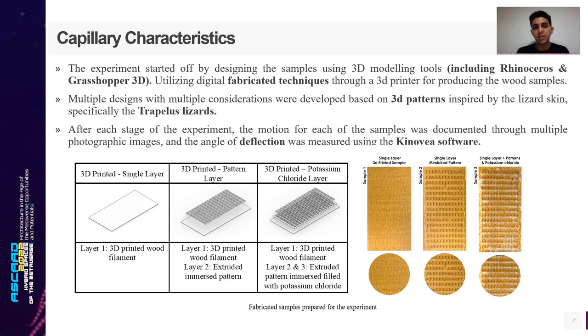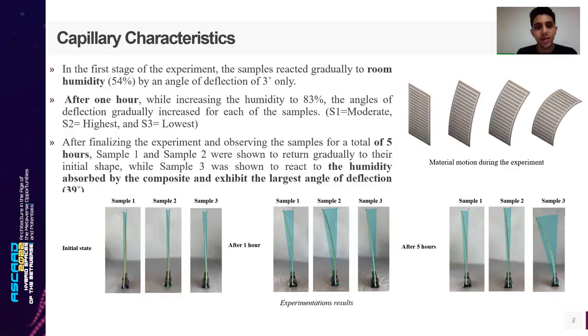After each stage of the experiment, Kinovea software was also used to measure the deflection angle of these samples. The samples are 3D printed samples, 3D printed samples with mimicked pattern, and 3D printed samples with mimicked pattern and potassium chloride composite. In the first stage of the experiment, the samples reacted gradually to room humidity by an angle of deflection of 3 degrees, but after 1 hour, while increasing the humidity to 83, the angles of deflection gradually increased for each of the samples, and the second sample recorded the highest angle of deflection.